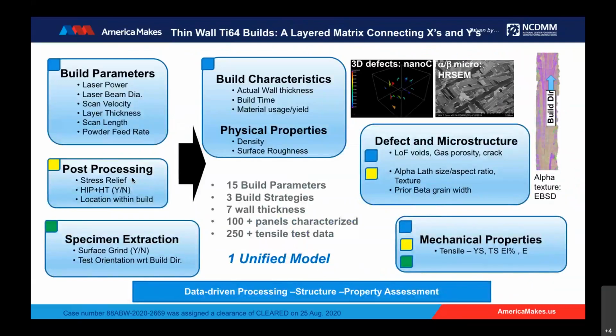Once we build the walls, we actually wanted to have an evaluation plan, right? So we have a layered matrix here connecting the X's and the Y's. So we have things like build parameters, post-processing, and the extraction strategies connected to the evaluation of the build DOEs. So things like the build characteristics such as wall thicknesses, build times, vertical usage, etc., can be directly connected to the build parameters like power, speed, feeds, beam diameters, etc. And so if you go one level deeper, quantifications of the defects in the microstructures like lack of fusions or gas porosities or the lath sizes or the grain size, etc., all of this can be connected back to the build parameters, but also with the post-processing steps. What kind of heat treatment the part sees, what kind of location that you're taking the part out of.